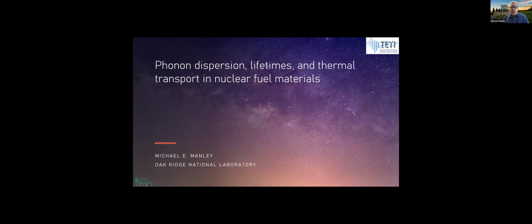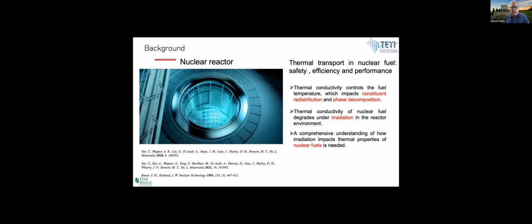Yeah, I'm going to talk about phonon dispersion, lifetimes, and thermal transport in nuclear fuel materials. IXS has been very important in the measurements of lattice dynamics in actinides for a long time now, since in many cases there are problems with isotopes as far as neutron scattering, the traditional technique. But thermal conductivity is actually a fairly important property in the operation of a reactor. The thermal conductivity controls the fuel temperature, which impacts constituent redistribution and phase decomposition and other things that are going to affect the performance of the fuel.